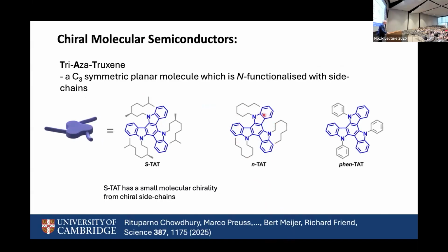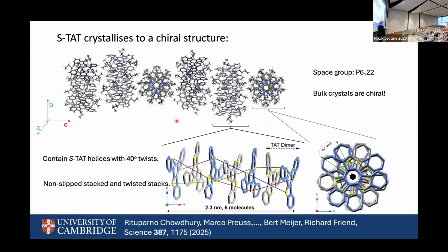And we're using planar molecules. They could be like little bits of graphene, except they've got some nitrogens in it, but don't worry about that. They're flat. But if you put some side chains on, they become quite soluble. And you can put chiral side chains on, which will give a handedness. You can make them S or R to give a preferred handedness. And if everything works wonderfully well, when you crystallize it, the planar semiconductor bits stack to form a column. The side chains hit the stack in the right twist. So you can end up with right-handed or left-handed screw threads.